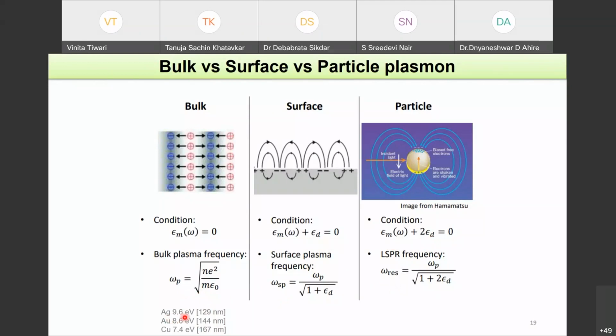So what you see here is that the bulk plasma frequency is basically a pure metallic property, and that is why these are all fixed. Silver has a plasma frequency of 9.6 electron volt, which is around 129 nanometer. Gold has 8.6 eV, which is around 144 nanometer. And copper has 7.4 eV, which is 167 nanometer.